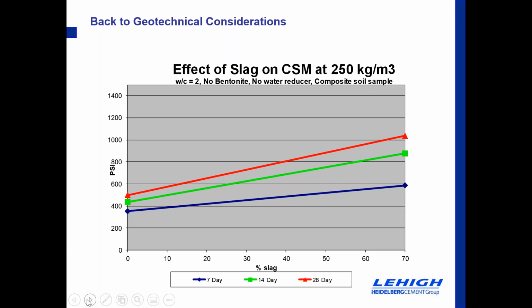So we very quickly realized that we could reduce the total cementitious amount and still end up within the desired results. So we then redid everything at 250 kilograms per cubic meter. Again, water cement ratio of 2, no bentonite, no water reducer, and just the natural soils. And here you can see that we were still well above target. Interestingly enough, the 100% Portland cement didn't really move that much. It stayed roughly where it was.